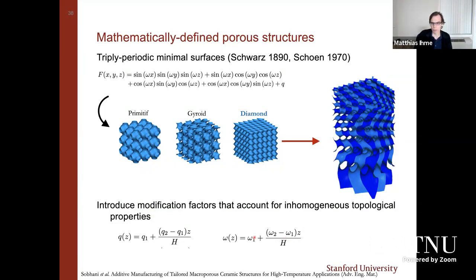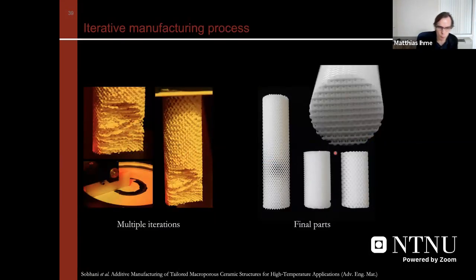So what we're seeing here is that we are imposing a linear gradation of this wavelength parameter and also a linear gradation of this offset parameter q. And with this, we can tune different parameters under constraints of porosity and pore diameter. This essentially turns out to be an optimization problem that is rather easy to solve computationally. Of course, the pore diameters that we are considering here are fairly small, somewhere between 200 micrometers to a few millimeters. This is still a rather challenging endeavor, simply for the reason that the pore diameters are rather small, and with this, the strut sizes are fairly small. This puts quite a bit of pressure on the process.